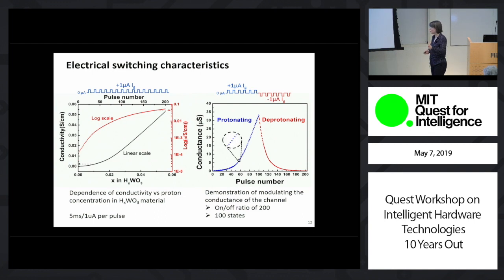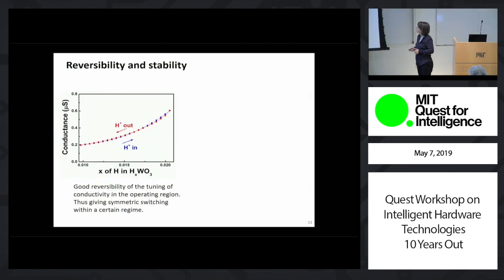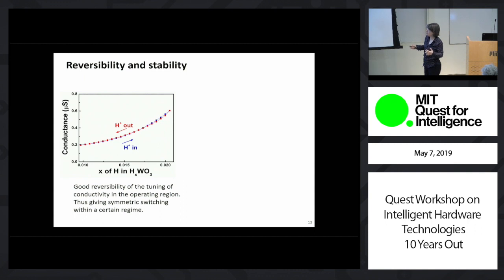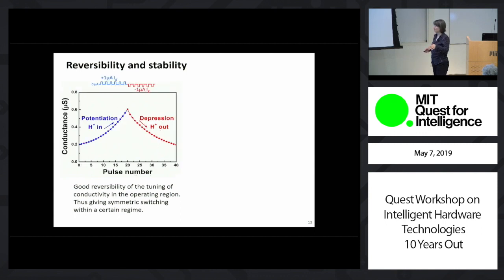If you reduce this pulse width to the microsecond-nanosecond regime, then you can fit many more states into this conductance range. Okay? It's also reversible, that again, by pulsing, we hydrogenate, by pulsing, we dehydrogenate, and within a certain regime of hydrogen content, the conductance response is reversible. That gives rise to symmetric potentiation and depression behavior, which is also promising for the reliability of these devices